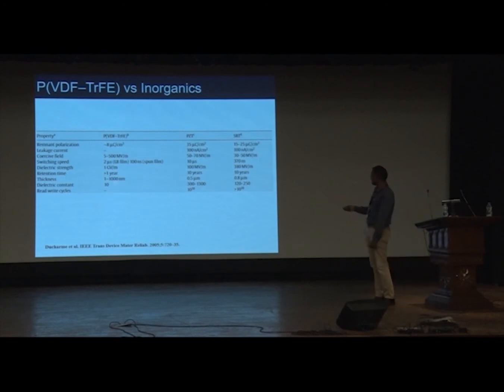Other than that, there are other parameters, but something called read and write cycles. So you can operate these inorganics for read and write cycles up to or beyond 10 to the power 10 cycles, which is a very large number of cycles. I mean, it's more than what you use. In case of PVDF, read and write cycles are not even 10 to the power 2 or 3, very small. So these are certain issues with PVDF on which we started to work.